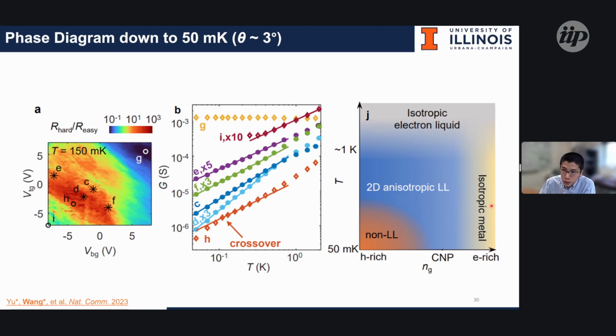you can see the isotropic magnetic behavior. Along the whole doping range at a very low temperature, you can see deviation of the Luttinger liquid behavior. We basically identify I point and H point here. You can see that the power law starts to deviate at very low temperature, which might be entering into another new context that hasn't been explored yet.